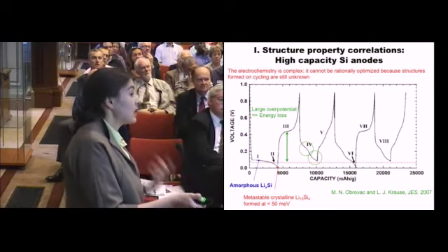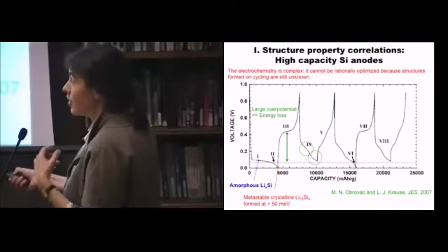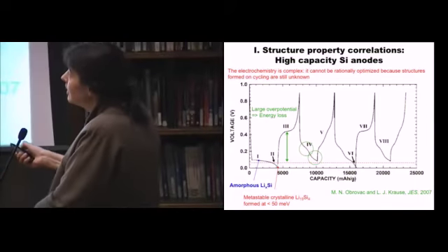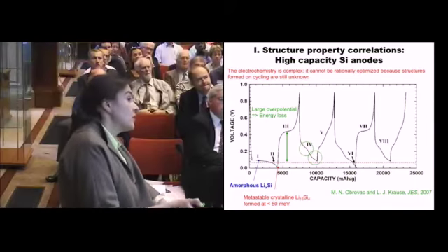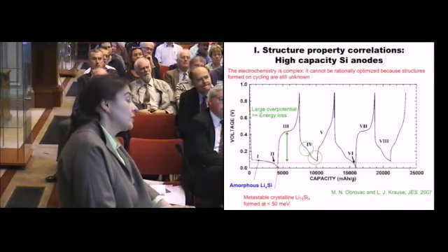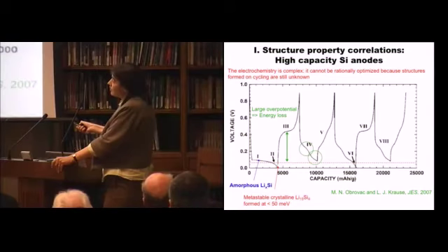And so this is bad news, because this gives you energy loss if you have a large hysteresis between the two. When you then discharge, you can see there are now two very different processes. If you go back, you actually see those processes again on charge. If you go down to low voltages, you go back with a very different procedure than you did in this cycle. So if you go to low voltages, you get this. If you go to intermediate voltages, you get something else.